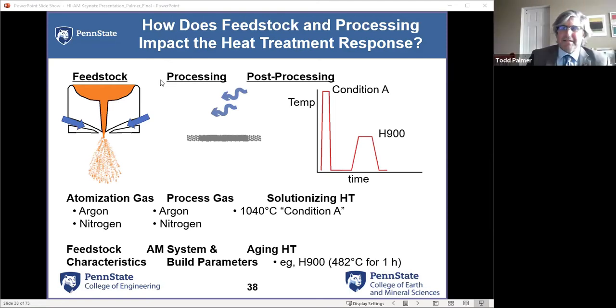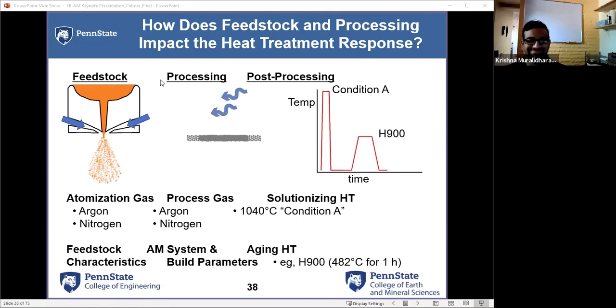And I'll add to Andy's there, and what he's seeing is there's oxides all through these powders. And if you look a little more closely at the actual as deposited and heat treated, there's oxides there too. And so Andy's working in duplex stainless steels, which have a combination of ferrite and austenite. And the oxide inclusions are actually acting as heterogeneous nucleation sites for austenite. So there's a lot of really interesting things, and Andy's going to publish a paper here soon that is going to track how these oxides change with post-processing. So the oxygen is a big deal. We've been ignoring it, like the smell from the rotting food in the refrigerator, but it's going to come out, and it's going to impact a lot of it.